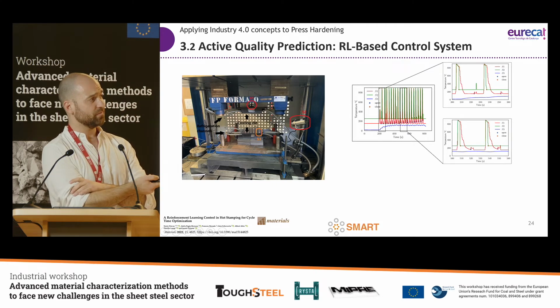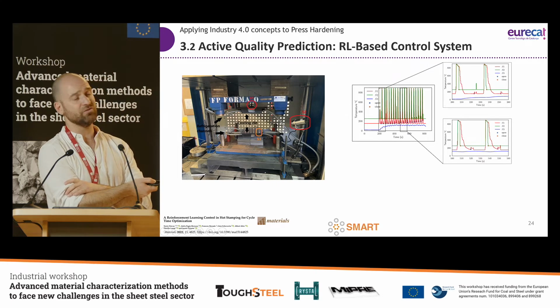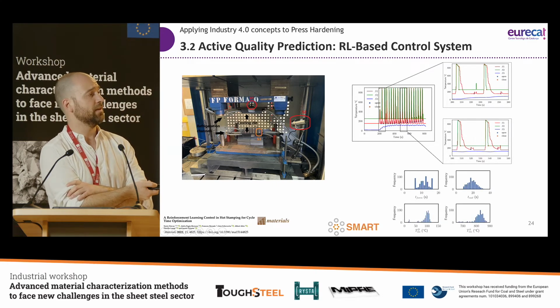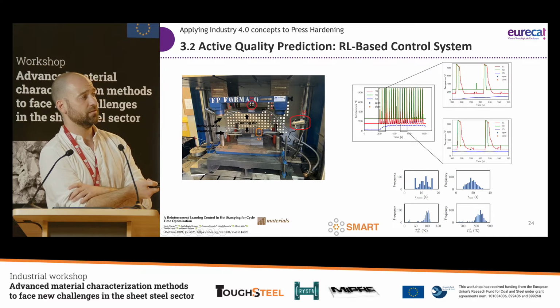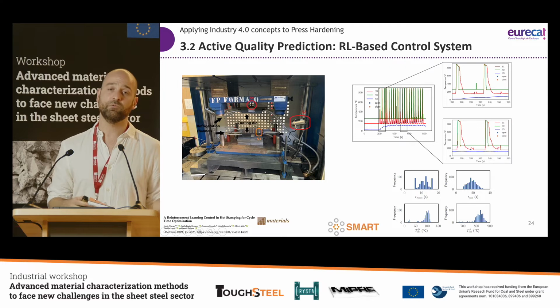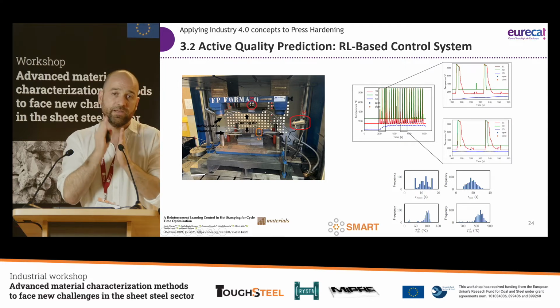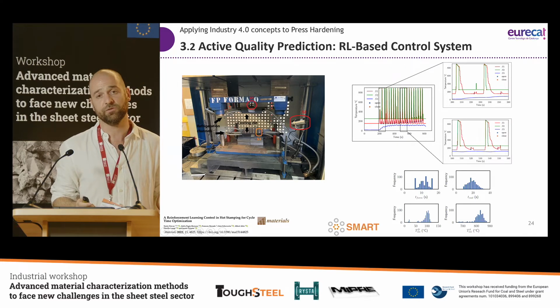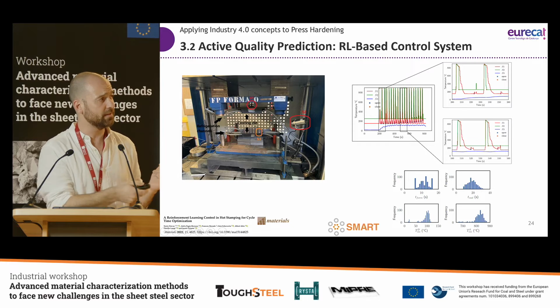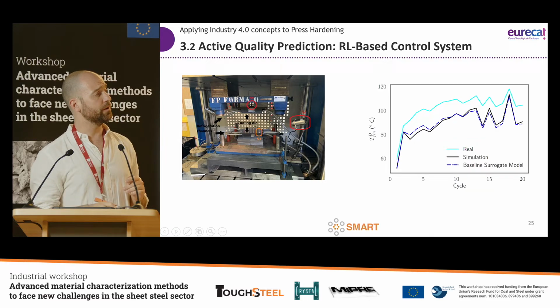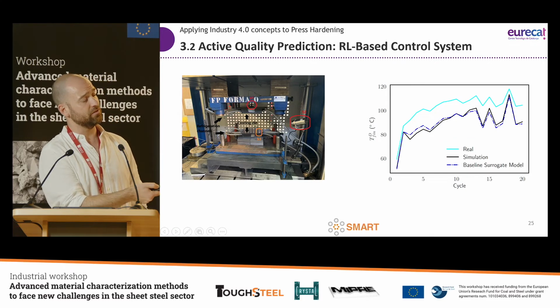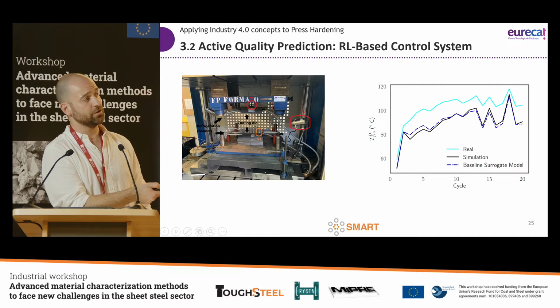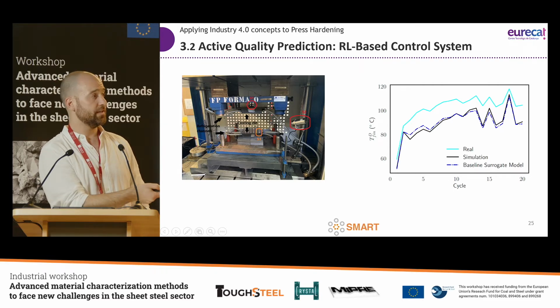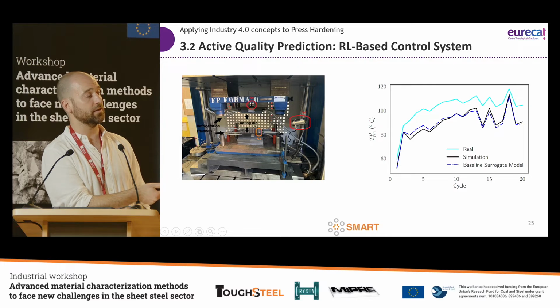As you can see, the signals are not as nice as we had at the beginning. And also here you can see a frequency distribution of the temperatures, initial temperatures, the transfer time, and so on. When we were simulating, everything was very closed and very well controlled. Here, because the simulation was very, very simplified, we have a lot of noise. So when we went to the actual system, it looks like this. This is what the simulation would have said is the final temperature. Here is what the agent said would be the final temperature, and here's the real system.